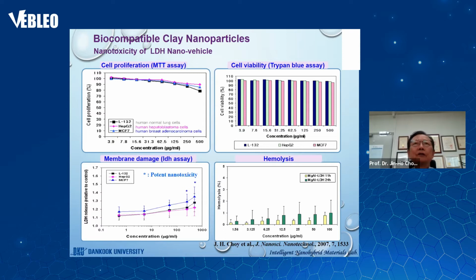And then we also checked the lactate dehydrogenase leakage test. What is lactate dehydrogenase? Lactate dehydrogenase is a kind of cytosolic enzyme. When the membrane is damaged or broken, the cytosolic enzyme could be released out, so we can measure the amount of released enzyme. As you can see here, the lactate dehydrogenase release is not that significant, up to 100 microgram per ml. Also we checked the hemolysis effect of our inorganic particles, and we found that the hemolysis is fairly negligible up to 100 microgram per ml. That's why our inorganic particle, the layered double hydroxide nanovehicle, could be applicable for drug delivery systems.